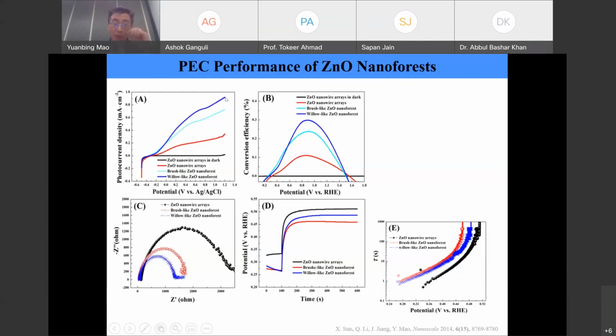So then we can convert this to conversion efficiency. And again, you will see that the willow-like zinc oxide nanoforest gives the highest conversion efficiency. And so, of course, I just showed you from the optical property aspect.